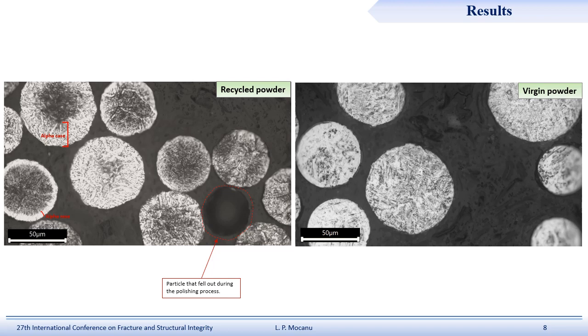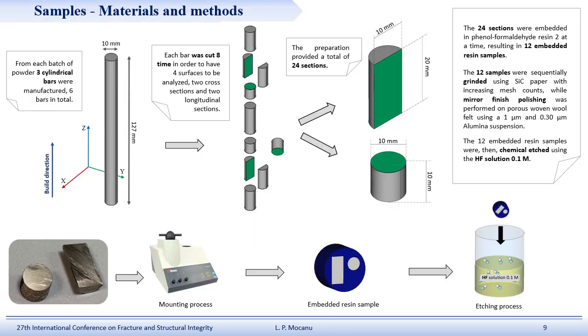And something interesting we found is this alpha case, which is a layer rich in oxygen around the powder particles. This is true only in the recycled powder. And this alpha case is also characterized by a higher hardness. But in order to properly investigate this topic, some other evaluations, such as the nano hardness test, are necessary.